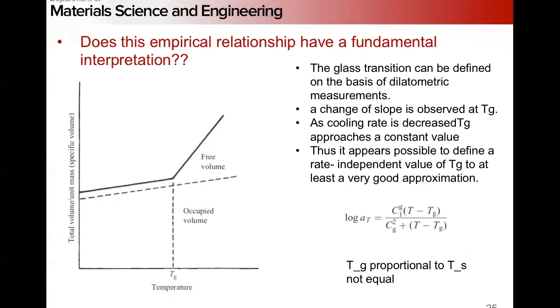I think in the reading I assigned, they said the difference between a cooling rate of a degree per minute and a cooling rate of a degree per day only gives you a couple hundredths of a degree Kelvin change in the position of the inflection. So it is possible to define a rate independent value of TG, and we can have a modified WLF where we put TG in here. TG is generally proportional to TS. It's not going to be exactly equal to it the way that it was defined before.